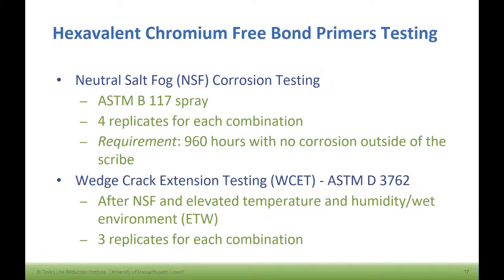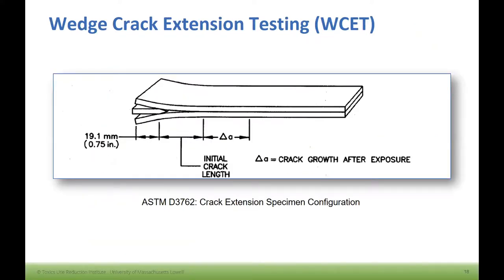For the testing, we did two types: neutral salt fog for the corrosion testing, and wedge crack extension testing. For those not familiar with the wedge crack extension test, we're trying to evaluate the integrity of the structural bond between the two aluminum substrates. You take a wedge and hammer it in between two bonded substrates, measure the initial crack length, and then measure how the crack grows and propagates over time. The stronger the bond, the less crack growth you'll see.